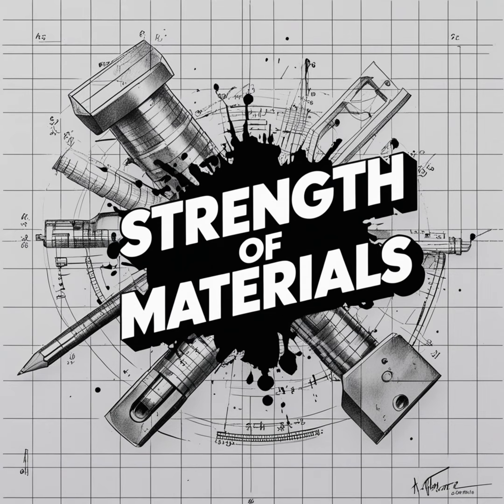Oh, I see. So they're like boulders sitting in the middle of our highway shoulder. Exactly. When you add more carbon, you are physically placing roadblocks in the path of the dislocations. The carbon physically pins the dislocations down, inhibiting the motion required for ductile deformation. So the traffic can't merge at all. Right. And the trade-off here is legendary in engineering. Adding carbon gives you a much stronger, harder steel that resists bending, but one that is infinitely more likely to shatter into pieces when it finally is pushed past its limit. It's like a blacksmith making a sword. You want it hard so it stays sharp, but not so hard that it shatters when you hit a shield. Exactly. It's a delicate balance.